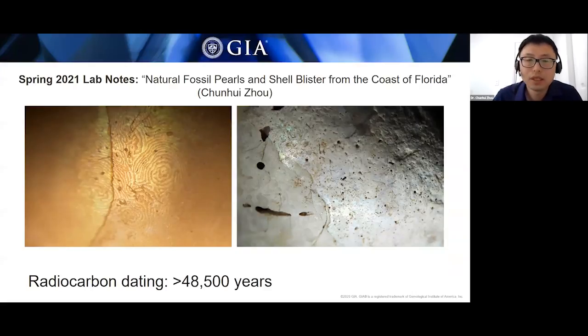So what we did is we sent some of the powders for carbon dating, and the results came back as pretty old. Actually, it's older than the instrument can tell, so older than almost 50,000 years. We don't know exactly how old these samples are. Maybe it could be much older than that, but at least we knew that these samples can be considered as fossil pearls. So this is the conclusion of these 3 samples.